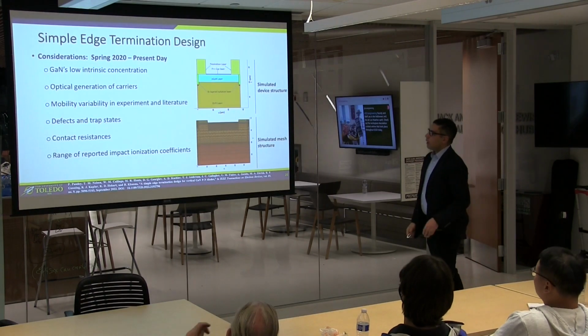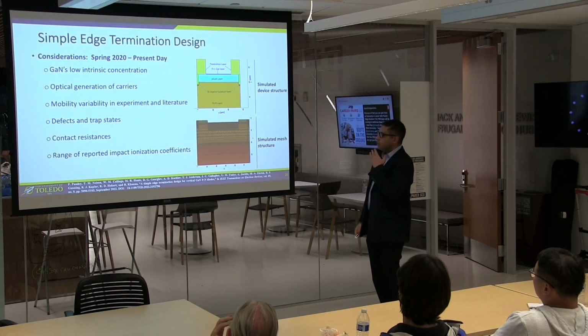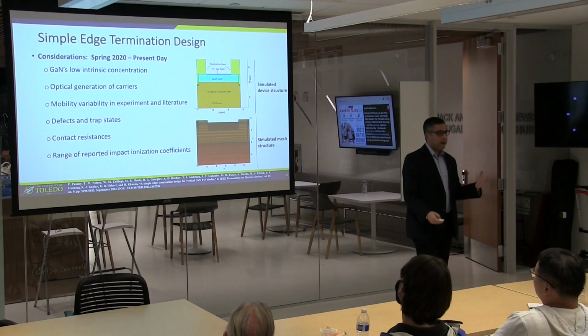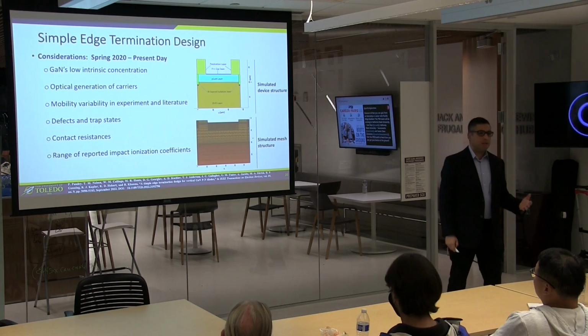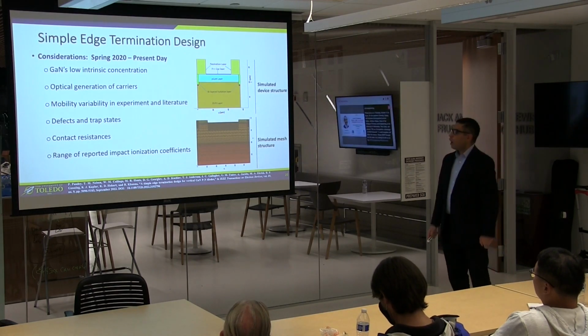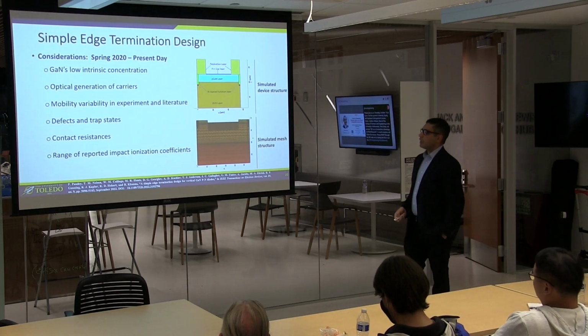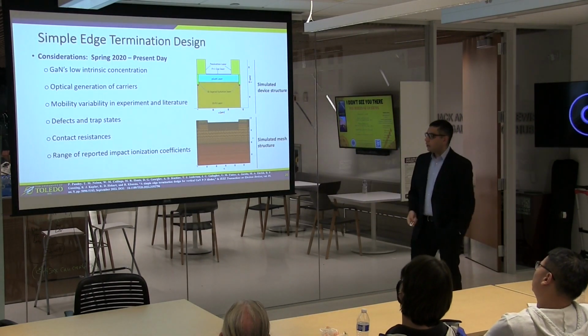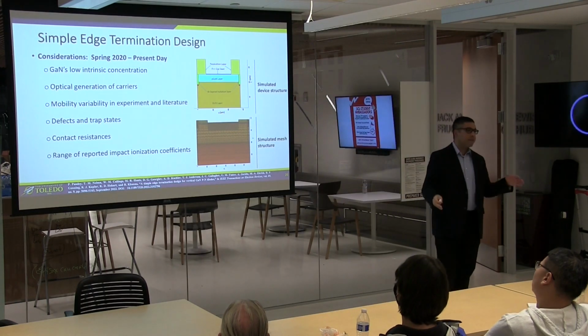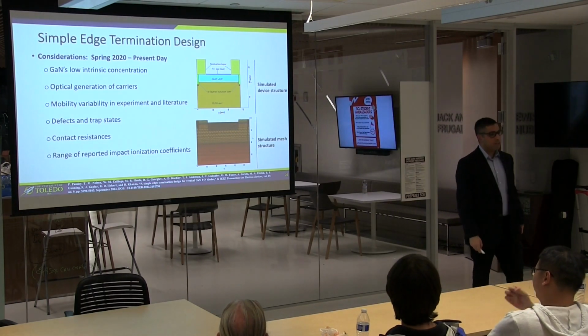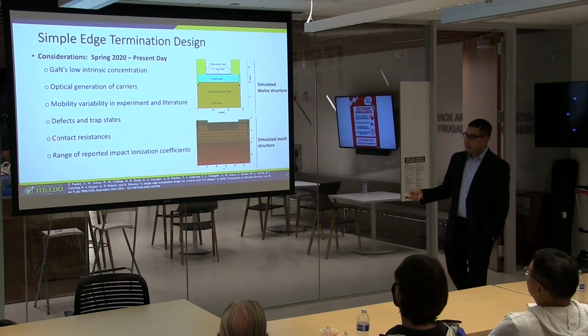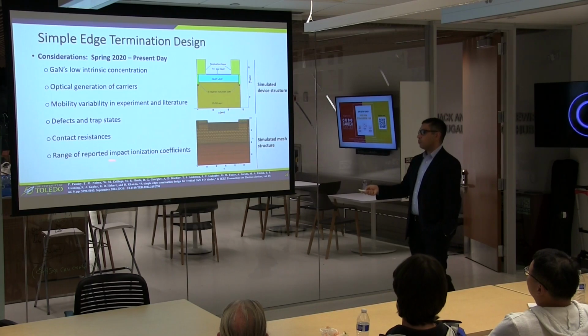So when you set out to make a TCAD model, finite element models, there's a lot of things that you have to consider. You want to consider GaN's low intrinsic concentration. You need to consider models for optical generation carriers. You need to consider the mobility variability, experiment and literature. There's a lot of differences between what you see in experiment and literature on those two topics. Defects and trap states, the contact resistance, and then of course the range of reported impact ionization coefficients.